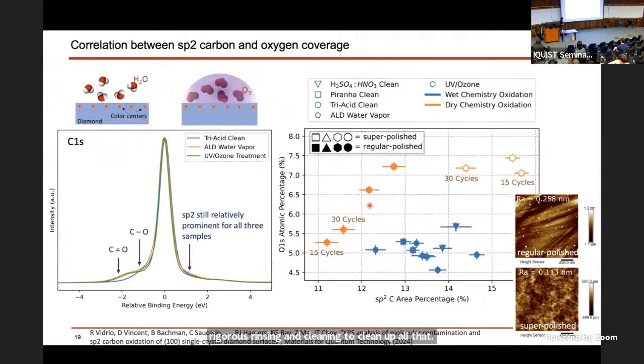And then another thing that we found, and in this study we tested about 8 different types of treatment methods, is a correlation in some cases between oxygen atomic percentage and the amount of sp2 carbon, which is graphitized carbon. Here we can separate the data into two categories. Diamonds that have been treated with mineral acids have data that is a little bit all over the place in terms of correlation with the amount of graphitic carbon, likely due to some amount of etching during the treatment, which depending on the etching time can lead to different levels of graphitic carbon. But all of these lead to moderate levels of oxygen coverage on the surface.